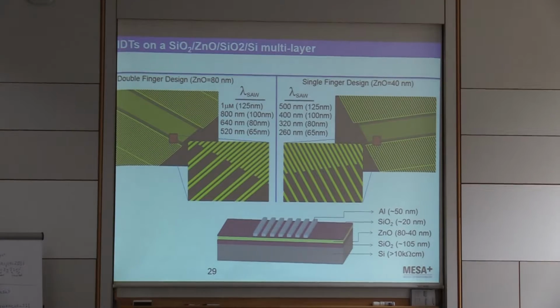Okay, so that was our basically first trial on silicon with a piezoelectric layer. Based on those results, there were a couple of improvements that we wanted to incorporate. First of all, if you have zinc oxide not protected, this is CMOS incompatible. Zinc oxide is also quite a tough material to work with, and very fragile and corrosive, basically. So we first of all try to make it CMOS compatible and also make our life a bit easier by putting a silicon oxide capping layer, just a small one.